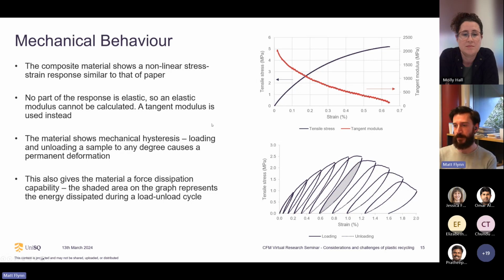And then doing a cyclical loading scheme here on the bottom, we can see that when it's loaded and then relaxed, it never recovers back to zero strain. It permanently deforms each time. No matter how little you deform it, it still returns back to a larger strain value than it started out as.